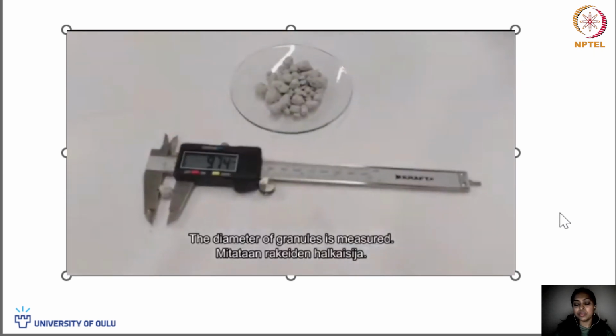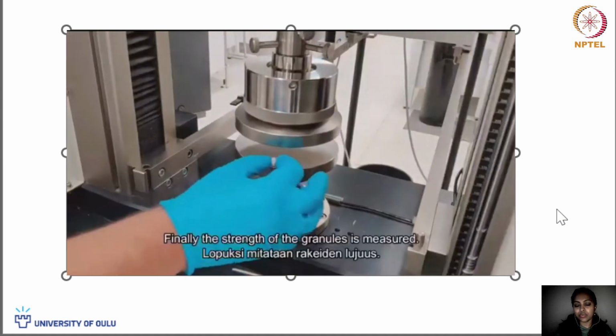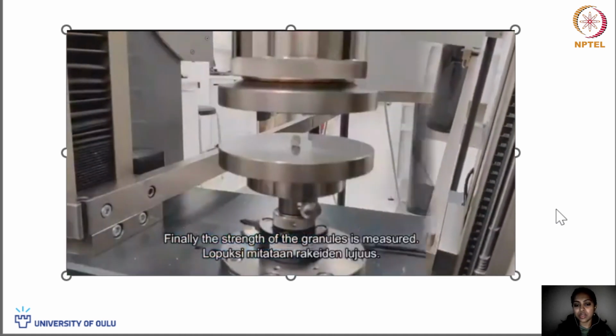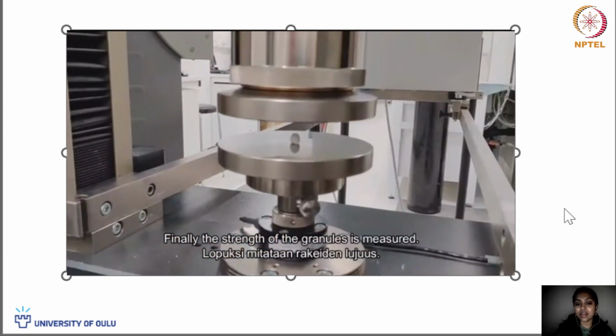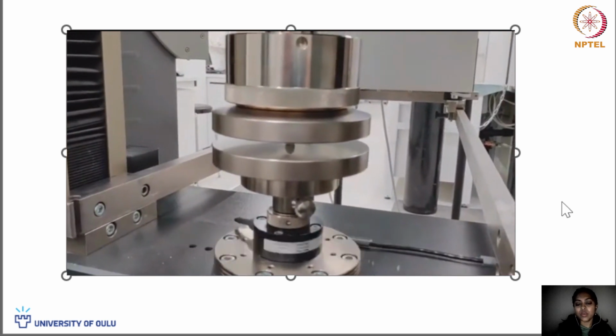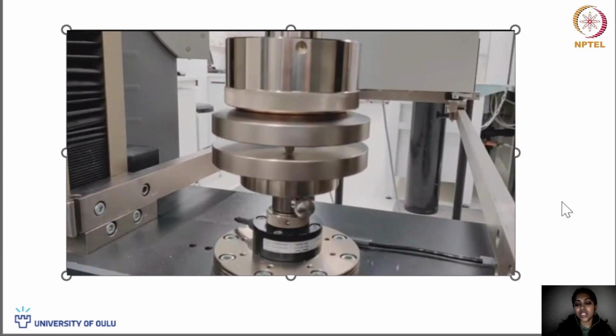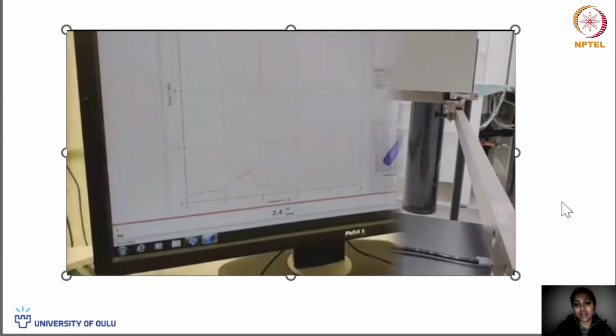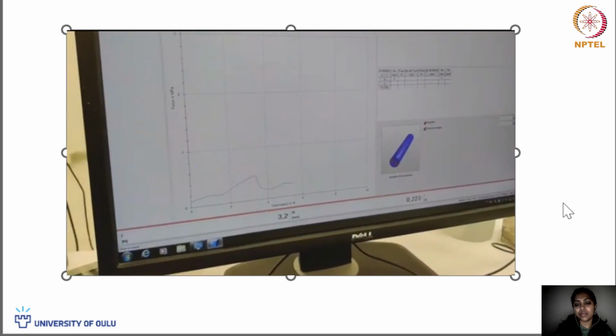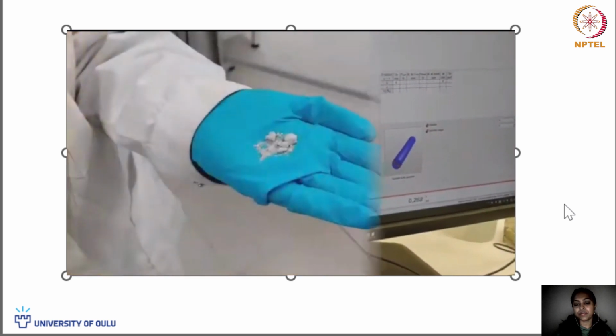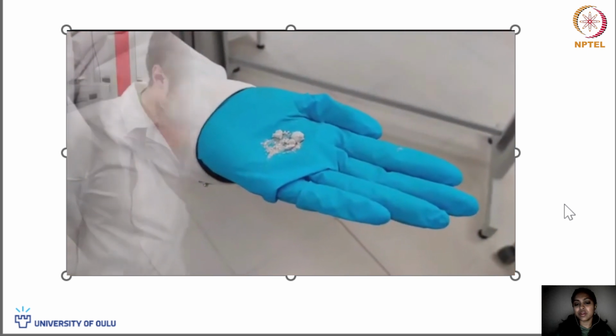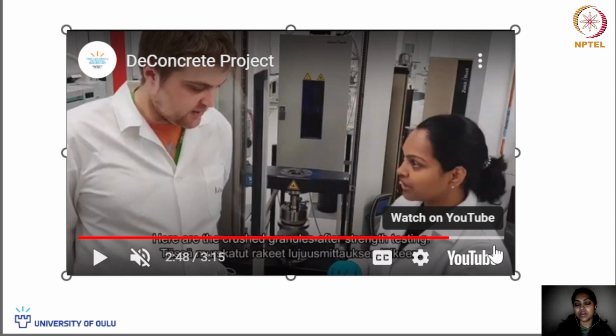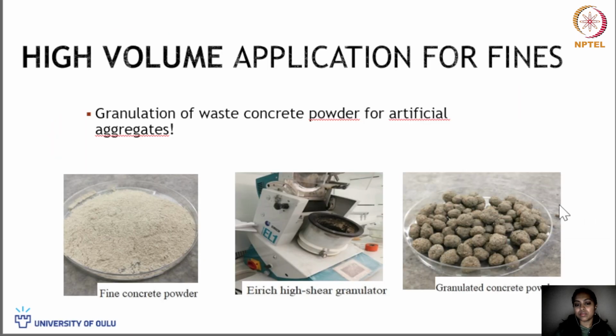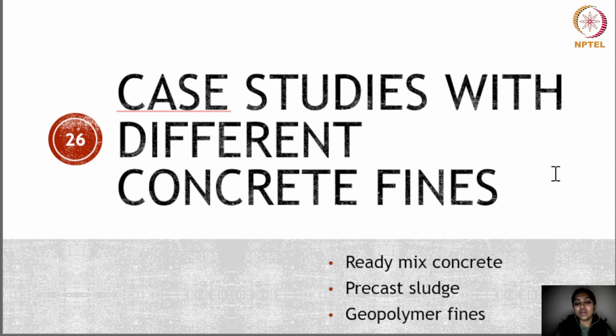Then we try to measure the strength of the granules. For that we measure the dimension of the granules in different directions because they are not exactly spherical. And then we measured the crushing value for at least 10 granules for each mix composition. This is after crushing the granules. So with this background idea, let's go now to the actual study that has been done.